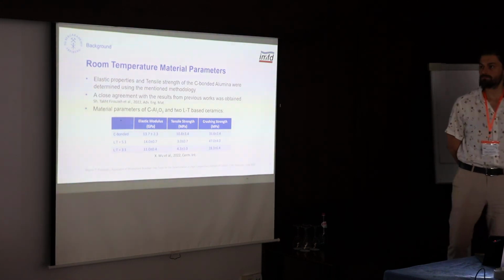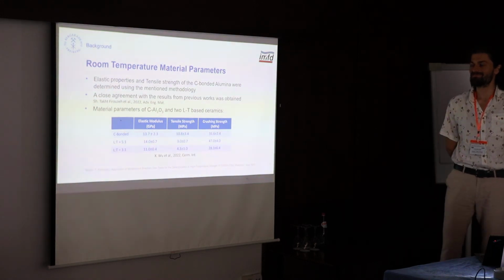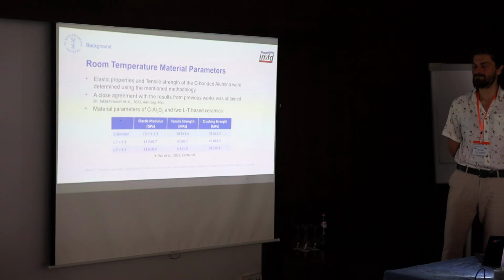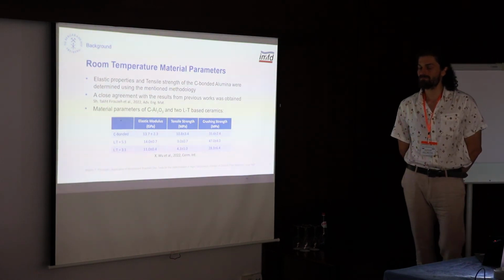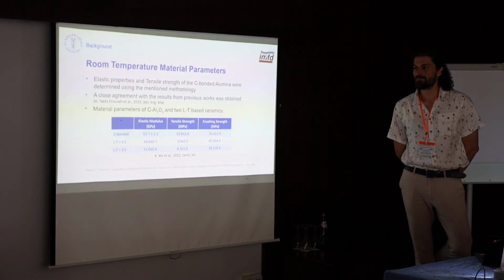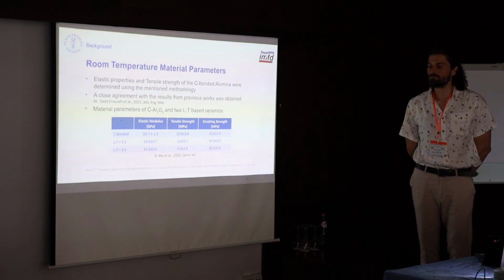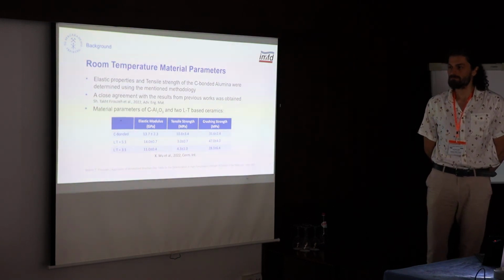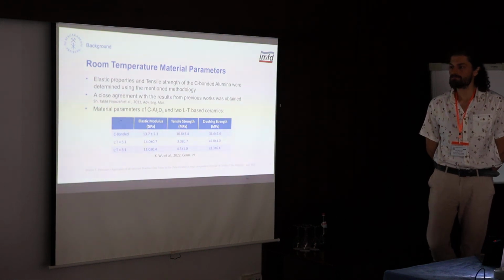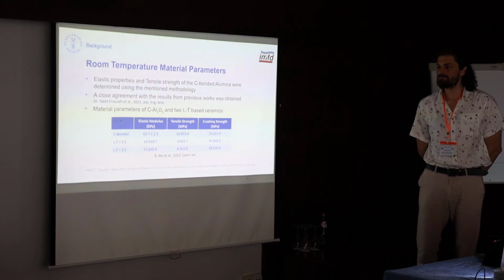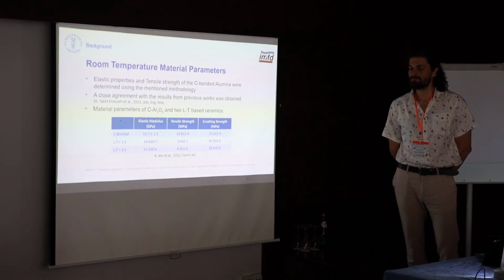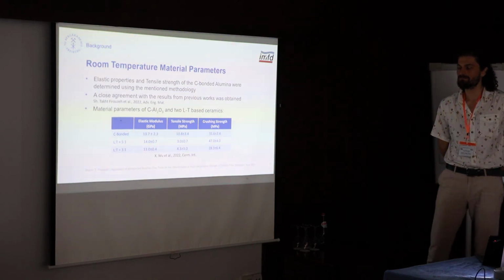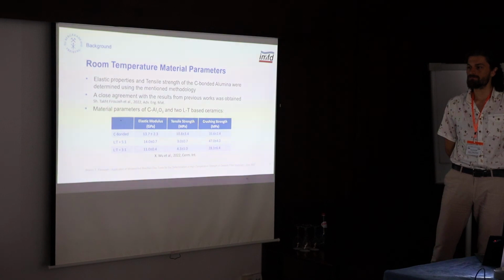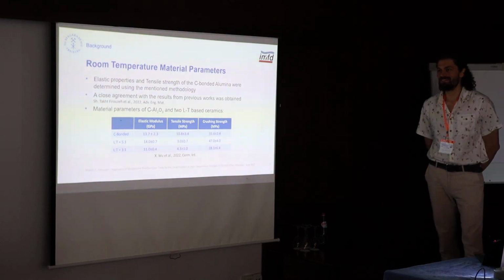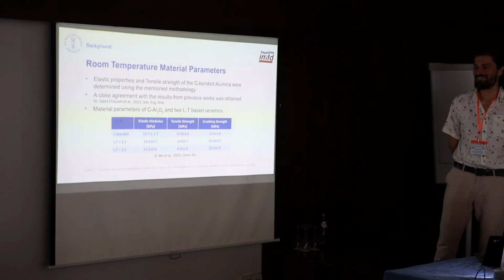I just wanted to make a comment about this problem of measurement at high temperatures. Of course, we have all this deformation of the ceramic loading parts and all this stuff. We had a similar situation, but we used only 4-point bending, and what we had were very thin ceramic rods going out of the oven, of the furnace. So this gave us a real displacement in the center. In this case it is probably more difficult, but still maybe it can be somehow calibrated. If you would know how your rods deform at high temperatures, then you can maybe subtract it.